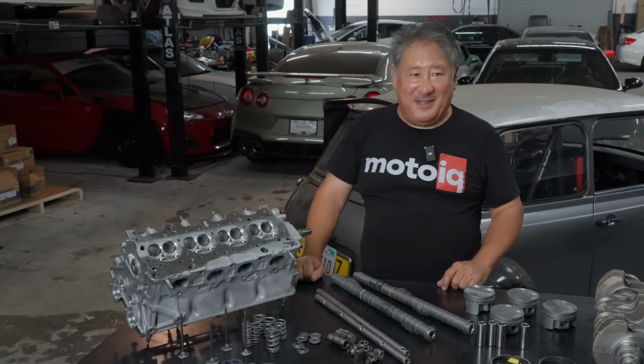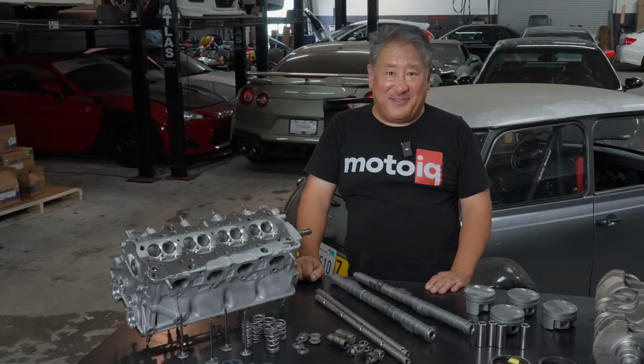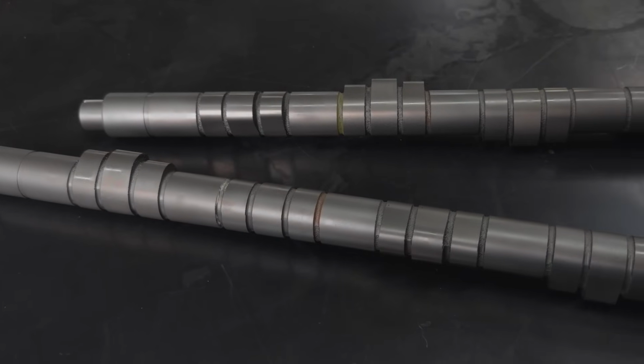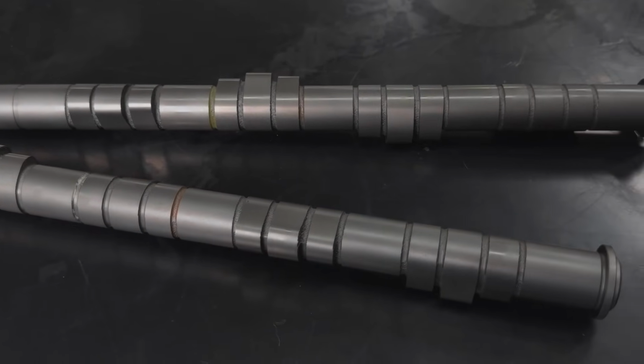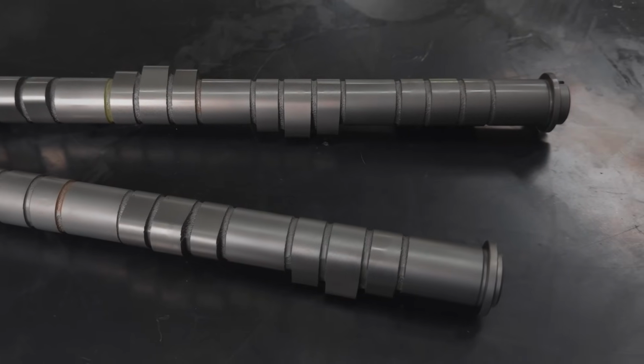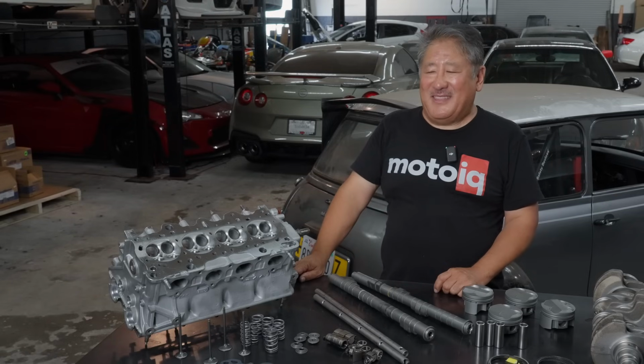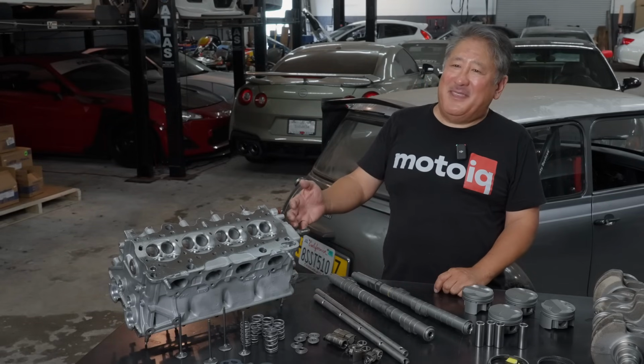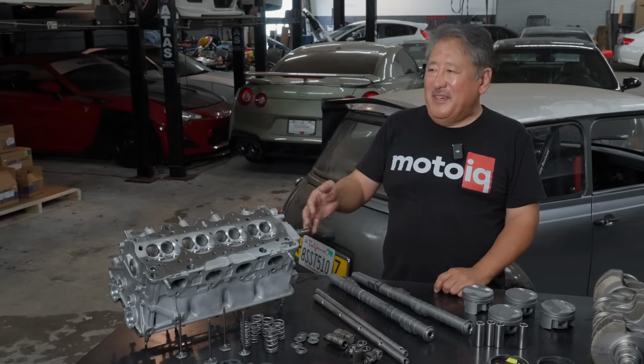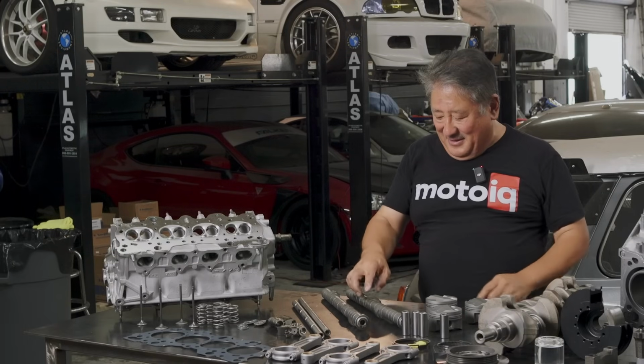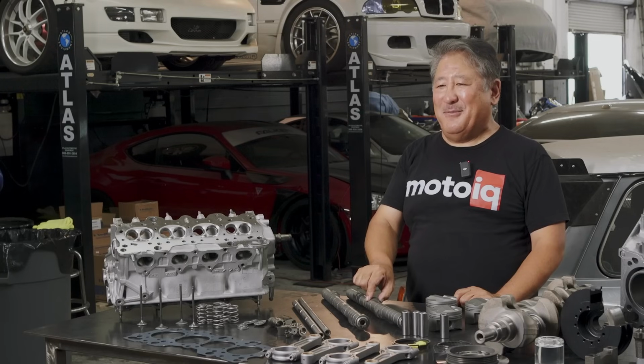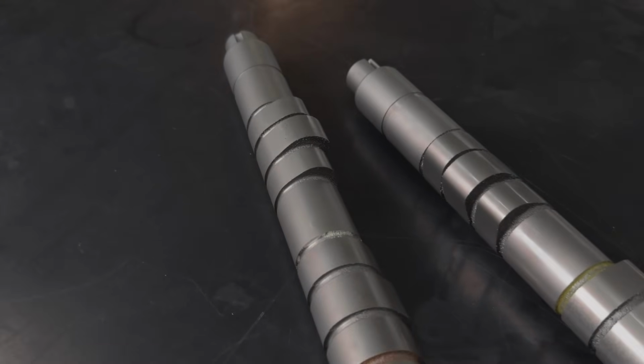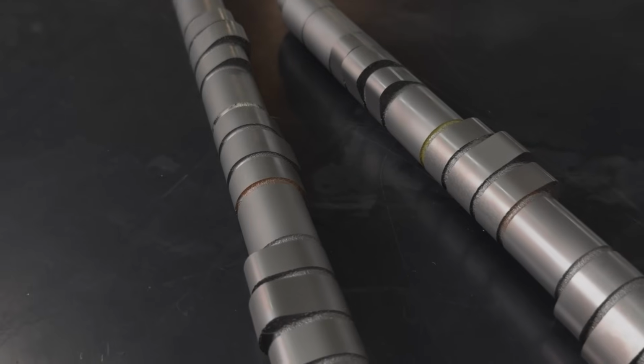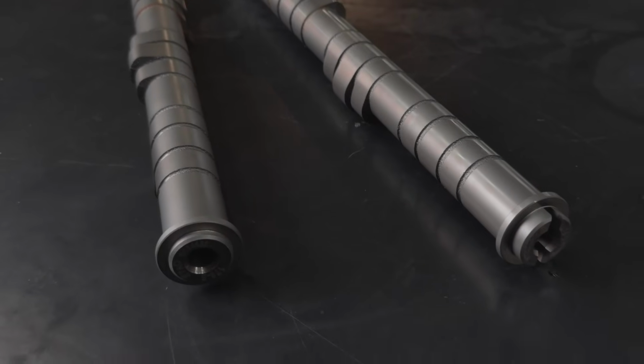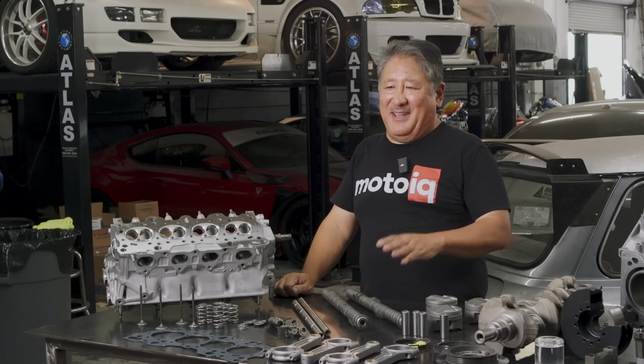For the valve train, we're going to start with the camshafts. We're using Kelford 176B cams. Now this is a great cam for a serious but maybe not full race motor. It can pull solidly to 9,000 RPM, but it'll still have good bottom end, good mid-range torque, and good idle. The VTEC system enables this. It has a low RPM lobe for putting around and a high RPM lobe for going fast. This cam is 284 degrees of intake duration and 280 degrees of exhaust duration, and has 11.8 millimeters lift on the intake and 11.4 on the exhaust. So it's a pretty short duration but high lift cam.